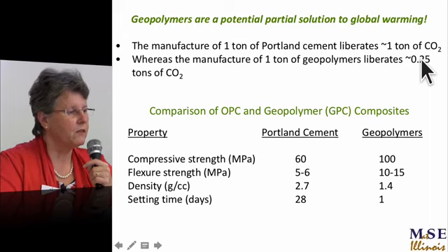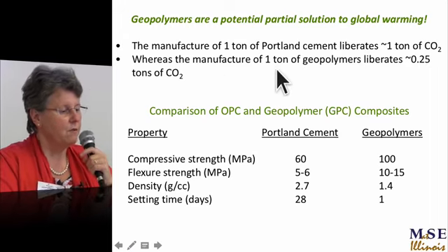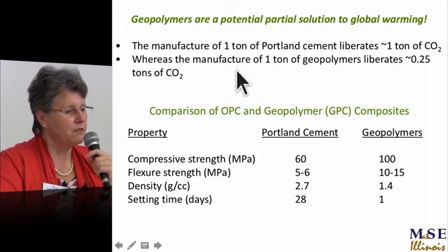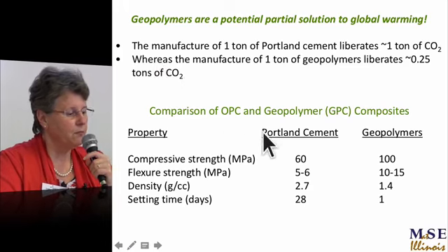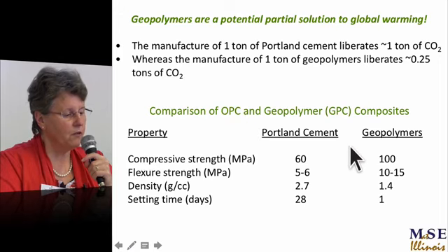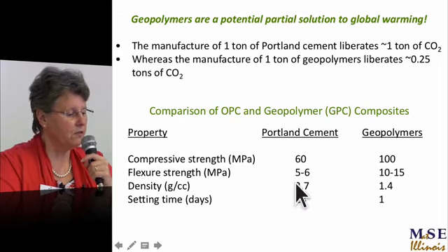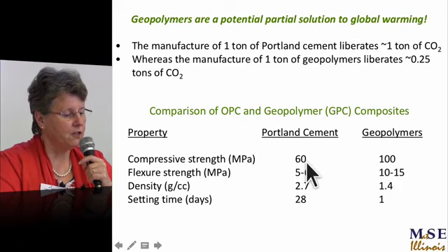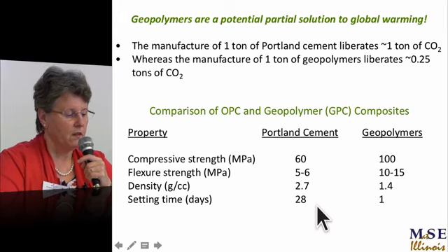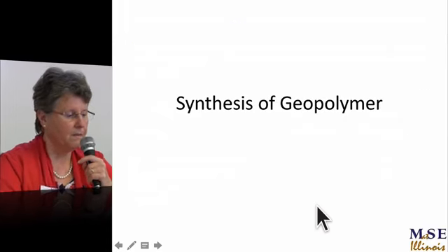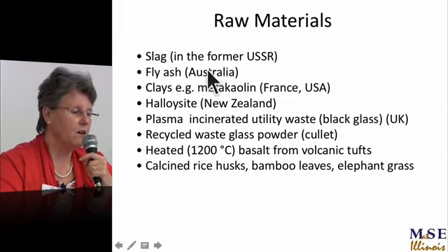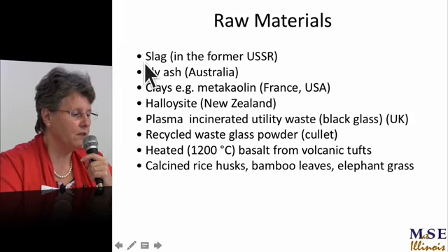1 tonne of Portland cement liberates 1 tonne of CO2, but to make 1 tonne of geopolymers, you only liberate about 1/4 of a tonne of CO2. And the mechanical properties between ordinary Portland cement and geopolymer composites: geopolymers are roughly twice the strength of cements in compression, 3 times the strength in flexure, half the density, and set to full strength in 1 day. So it's the synthesis. So here's a different list over the years.